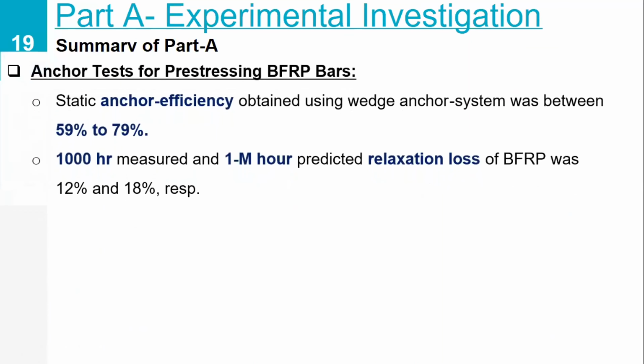So basically, coming to the summary of the first part of the work, which is on the experimental investigation. We conducted the anchor efficiency test of the mechanical wedge anchors and found it to be between 59 to 79%, which is still acceptable for pre-stressing applications because the ACI code recommends about 50% of the initial pre-stress of 50% of the ultimate strength, and the 1,000-hour relaxation loss and the 1 million hour predicted relaxation loss were between around 12% and 18% respectively.